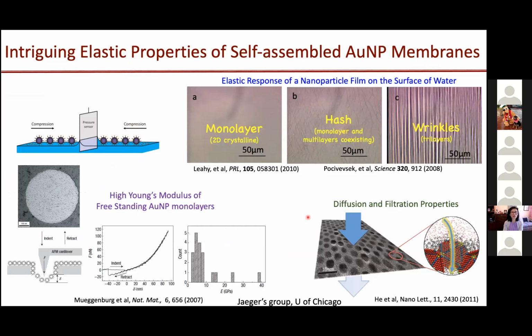Professor Jaeger's group from University of Chicago transferred those films onto a TEM grid, forming freestanding films, and measured the Young's modulus, finding it to be quite high—on the gigapascal level, even stronger than nylon and most plastic films. In fact, they really can sustain high pressure during tests of solvent filtration.